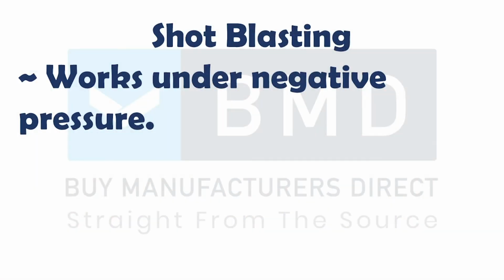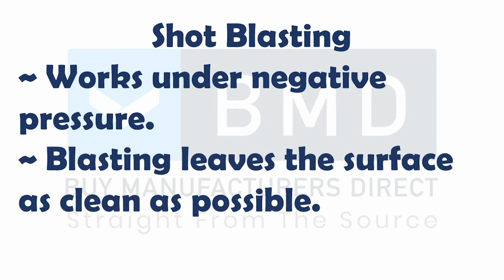So what that means is the waste that it makes while it's working is immediately evacuated from the area where it's been created. So that floor is as clean as it can possibly be. It cannot be made any cleaner by vacuuming it. No matter how many times it's vacuumed, like after grinding, the floor is as clean as it can be. So when the coating is applied to the floor, it has the ability to absorb into the surface until the viscosity gets to the point where it can't absorb any further, which is why moisture vapor systems are going to be specified by the manufacturer to have a surface shot blasted.